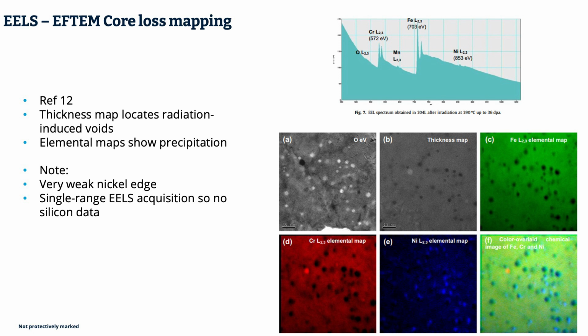Now, this is the same sort of data we saw earlier on, acquired with EDX on the irradiated AGR fuel cladding, but illustrates that because the ionization edges for the different elements are scattered across such a wide energy range in EELS, they weren't able to carry out the analysis for silicon using this method, or at least not in the same data set. A separate, totally separate data set would have been needed to do that.